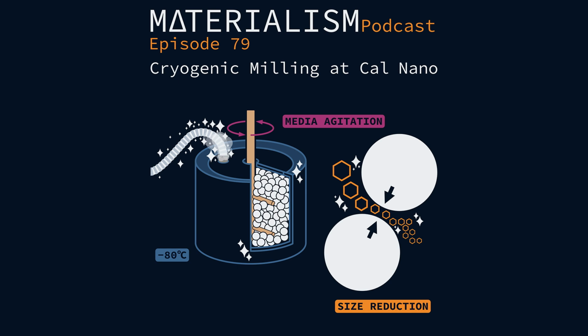I think silicon nitride is the case study here, where they first tried to make it and they couldn't get the theoretical properties because of small trace impurities that were almost beyond the detectable limit. Oh, yeah. And what they ended up having to do was make some silicon nitride media and start using that. And then that next batch is your new silicon nitride media. And all of a sudden you slowly start working out those impurities.